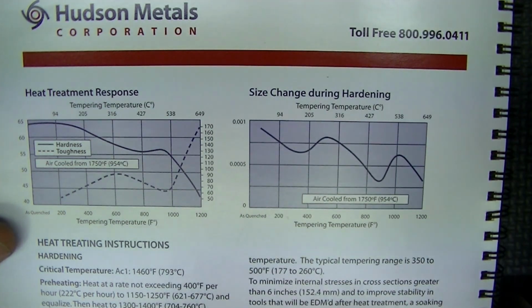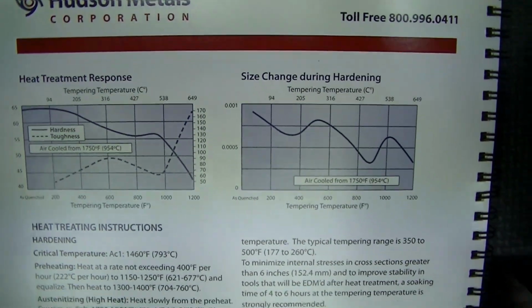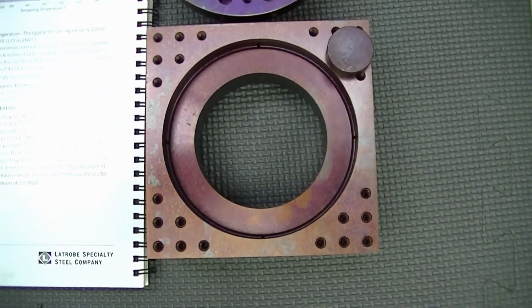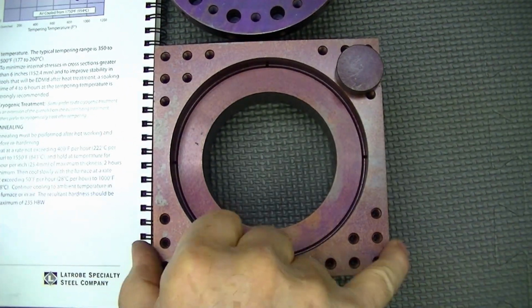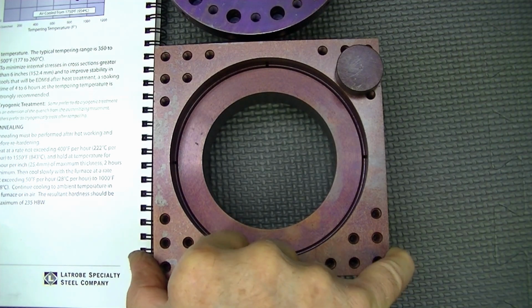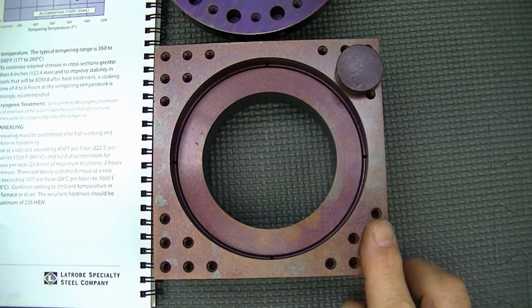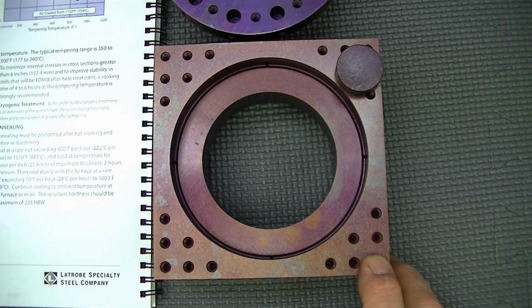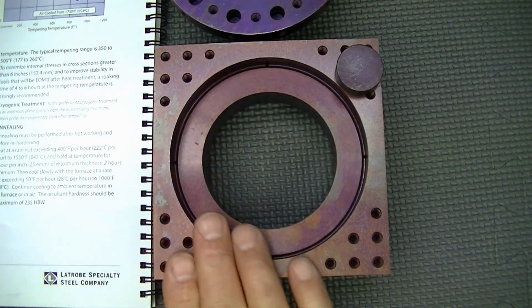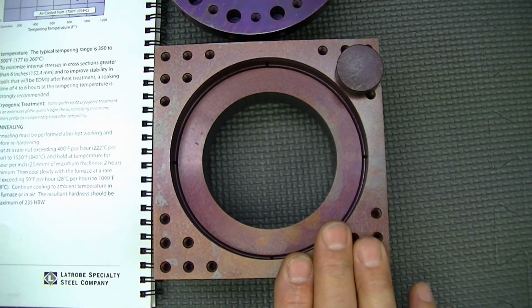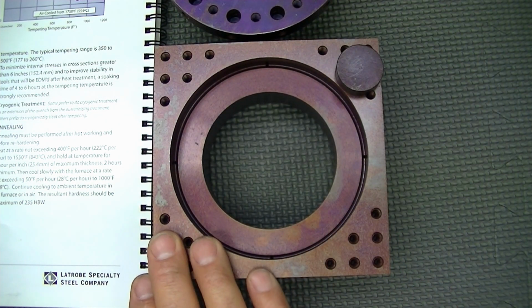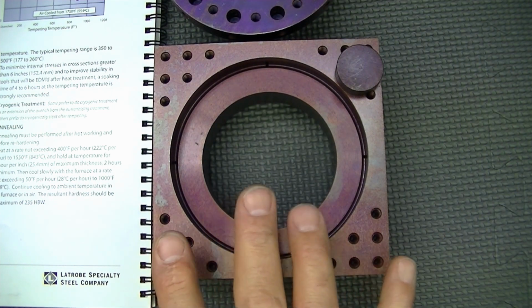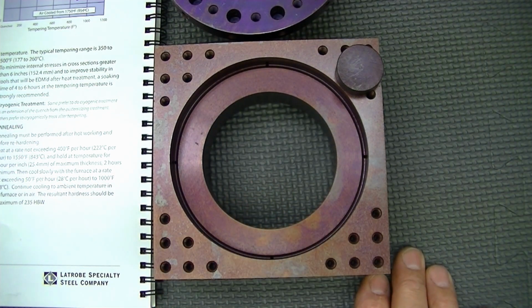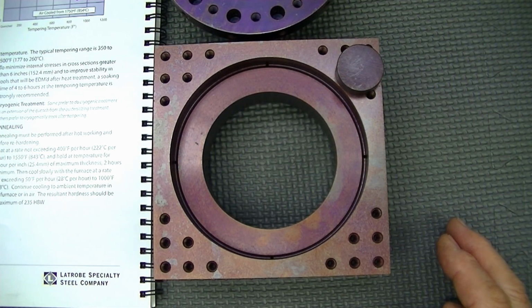But it's better to historically know from pieces, like taking this piece itself, measuring pieces beforehand and recording what they were, and when they come back measuring what they are, and we know historically that A2 actually has a tendency to be closer to 1,000th of an inch per inch, or 0.1% growth. So all of the dimensions on everything I make in this are compensated to be 0.999 of the actual dimensions, so that when it's heat treated, it's actually at the sizes that we want. So we're making it smaller because it's going to grow, and that's what you have.